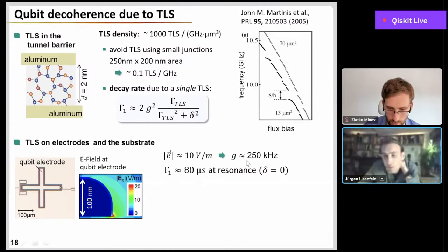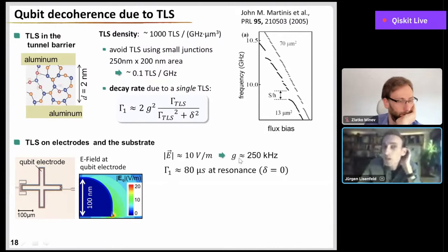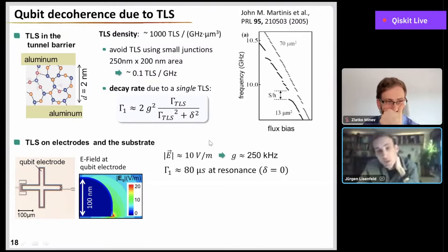And this would correspond to a coupling strength now of only 250 kilohertz. So much less than these 50 megahertz that I quoted for these junction defects. And accordingly, such a defect, even at resonance, would only limit the T1 time to 80 microseconds. But how likely is it now to have a defect at resonance?